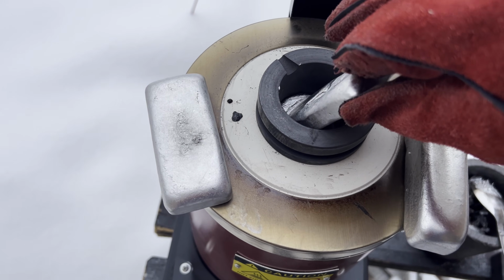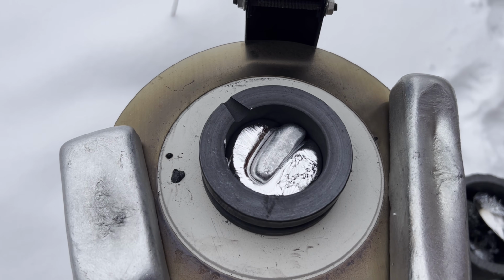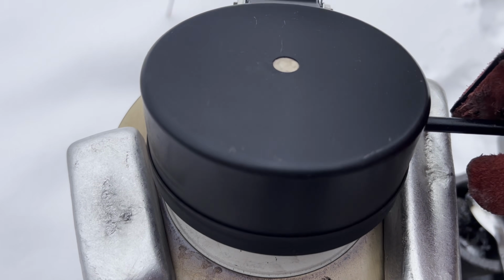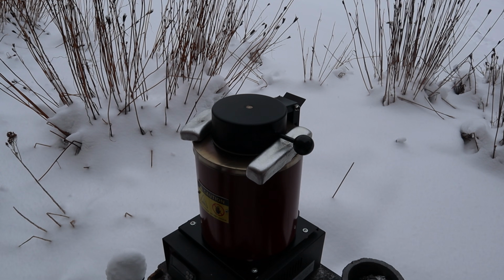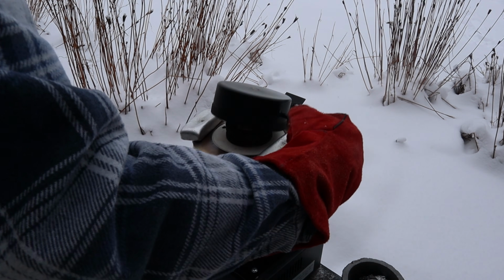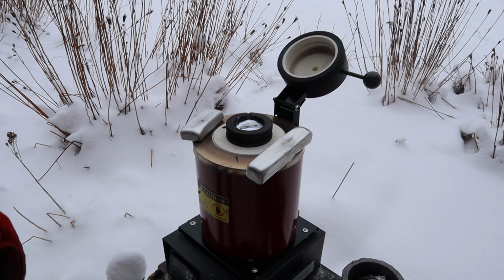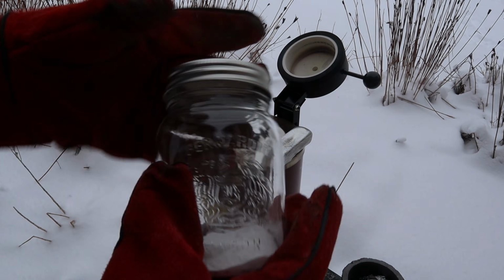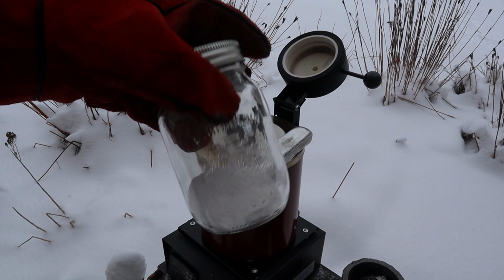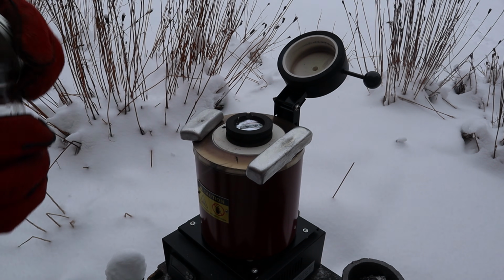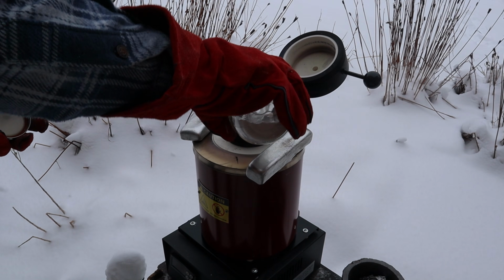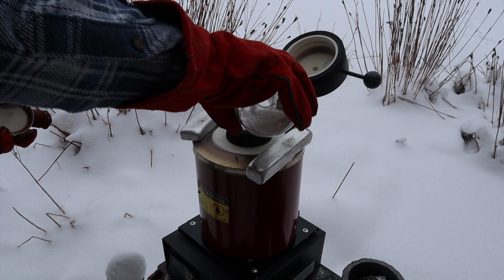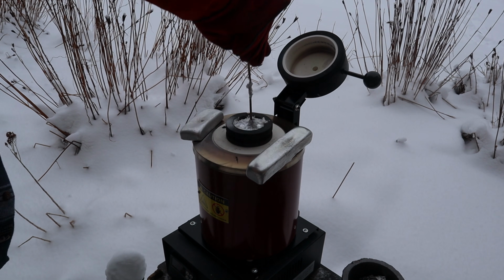The temperature that I found works really well for melting and pouring aluminum is 760 degrees Celsius. It's about 100 degrees higher than the melting point of aluminum. But since it's cold out today, I've set it just a little bit higher so it still flows really well. This is sodium carbonate. It's super easy to make on the stove just by cooking regular baking soda until it stops gassing off. It's going to act as a flux for our aluminum.